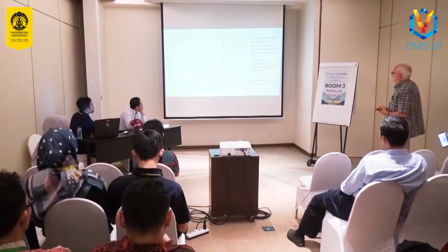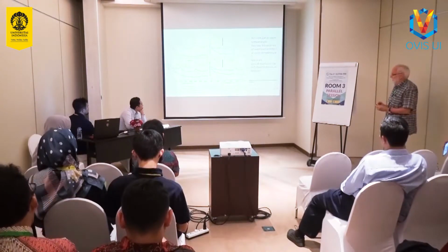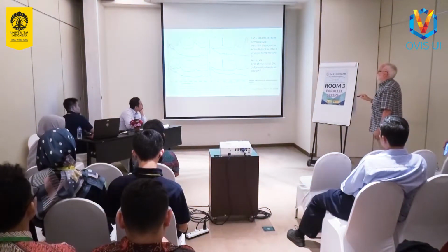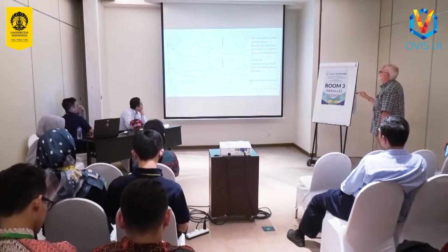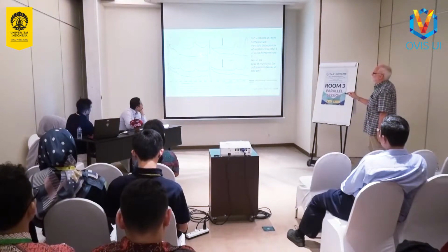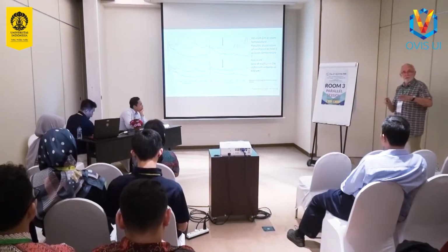Now, the first thing we did was say, well, what happens to methanol at room temperature? If you put methanol at room temperature into zeolite hydrogen Y, to explain the spectrum a little bit, the bottom trace is the spectrum of the zeolite, empty. These are inelastic neutron scattering spectra, so they're like infrared spectra, plotting intensity versus wave number. Here's the spectrum of the empty zeolite Y, not ZSM-5, but zeolite Y. Here's the OH vibrations of the zeolite. So there are weak bands there, and an OH bending mode down here, but otherwise there's really nothing there. The zeolite doesn't contain much hydrogen, just a few hydroxyl groups.